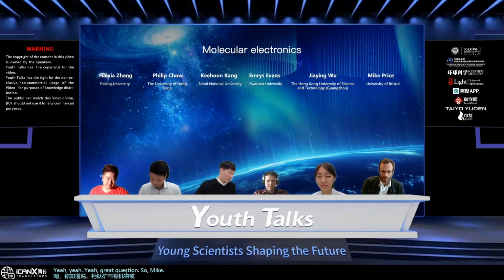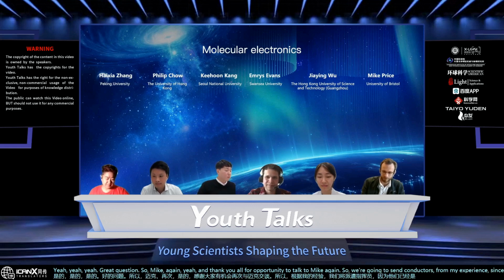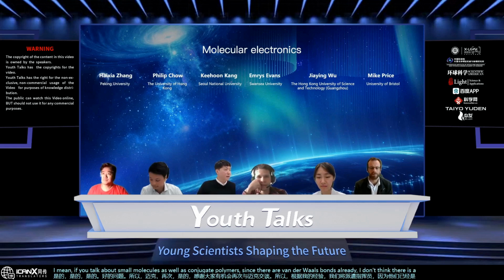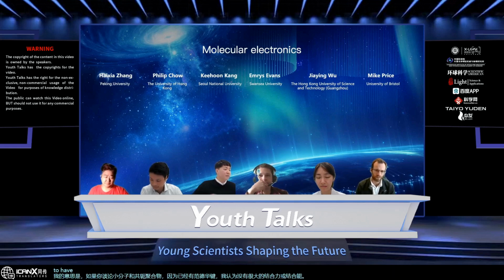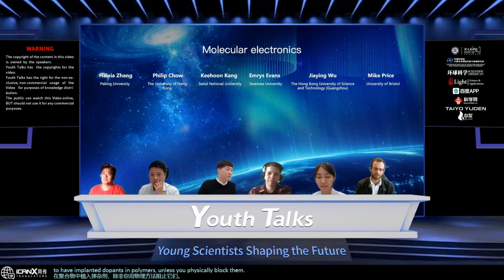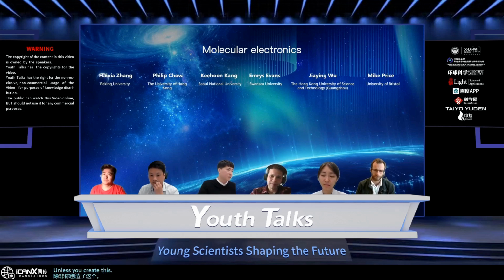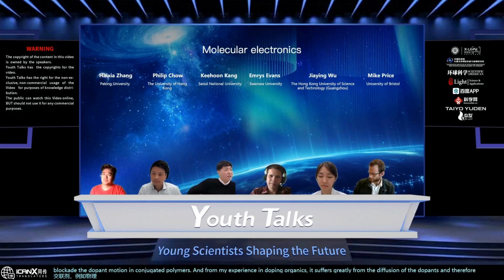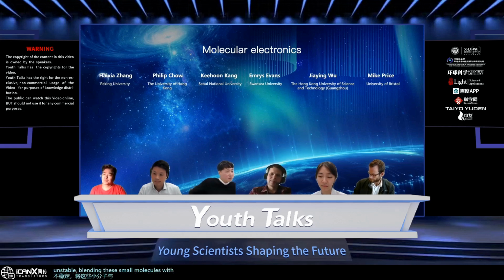Great question. So Mike again, and thank you all for the opportunity to talk to Mike again. So organic semiconductors, from my experience, since they are already van der Waals bonded, if you talk about small molecules as well as conjugated polymers, I don't think there is a great binding force or binding energy to have implanted dopants in polymers, unless you physically block them, unless you create crosslinkers, for example, to physically blockade the dopant motion in conjugated polymers. And from my experience in doping organics, it suffers greatly from the diffusion of the dopants. And therefore, it can be very thermally unstable, blending these small molecule dopants with polymers for solar cells, for example, when you use it for heterojunctions.